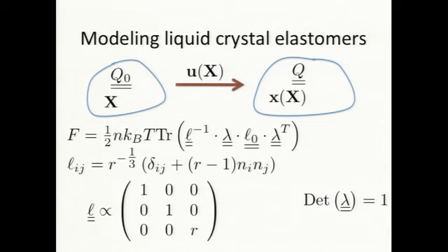They're L's, not Q's, for two reasons. The first is simply that Q reflects the nematic order, but these reflect not the nematic order, but the coupling between the nematic order and the polymers. So if there was no coupling, these would have to disappear, even though Q hadn't disappeared. And secondly, because if there was no coupling, these disappearing means going to identity, not going to naught. So in fact, L is a simple uniaxial tensor. It just points along n, which is the liquid crystal direction. So in its diagonal frame, it really is just 1, 1, and then some anisotropy.